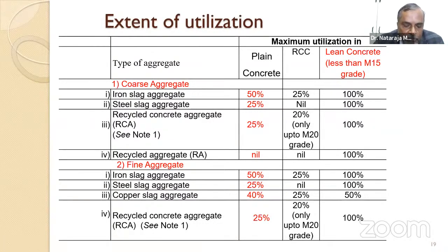100% of these types of unconventional materials should be recommended. And if you see many of the technical papers which we have published over 10-15 years in the past, they are all with 100% replacement of the aggregates. And of course, we also used some 20, 40, 60% just to tell you where exactly certain parameters become optimum. But otherwise, even if you use 100% of the aggregate, you may have a problem of workability.